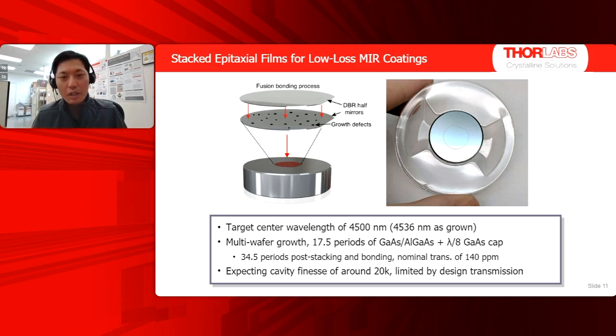And so our very first go at it, we were conservative. We designed for a nominal transmission of 140 ppm, so certainly by no means supermirror levels of performance, but we wanted to start somewhere, right? And be able to check out this technique. And it turns out that it worked very well. At the design transmission of 140 ppm, that actually gives you a cavity finesse of 20,000, and that is solely limited by our design choice of such a high transmission. And that gave us hope that we can do well with these types of coatings.